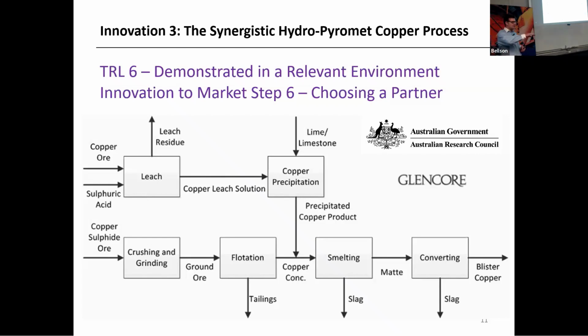Normally you leach and then you do solvent extraction and electrowinning, but we said, okay, we'll get rid of the solvent extraction and electrowinning. We'll just leach and precipitate copper hydroxide using calcium carbonate, which is a low-cost reagent, and then you get this powder that you could blend into a smelter feed to get extra copper through the smelter, recovered from the leaching process, and cool it down. That was the subject of an ARC linkage project, and a PhD student graduated having worked on that for a few years, and it was developed to a point with Xstrata and then Glencore.